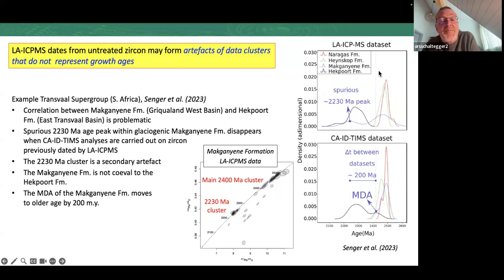Discordia. Yeah, I've never actually seen common lead in zircon using LA-ICPMS, provided, of course, you pre-ablate, which everybody does. The common lead should just be on the surface. As you mentioned before, zircon itself has negligible common lead, so that's really a big issue. Yeah, it's not true, because when you have slight alteration of the zircon, you may see or you may not see in the... Oh, that's true. Then you're really in trouble because you probably got lead loss. There may be inclusions too. Yeah. No, it's a nightmare.